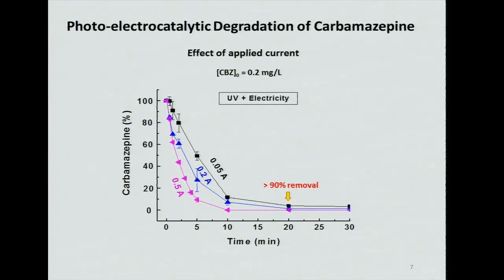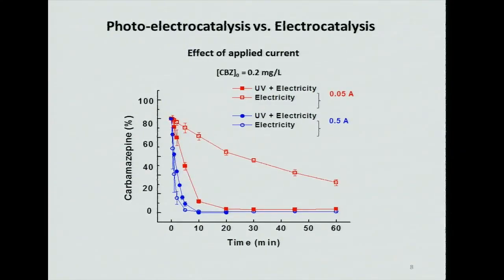Here are the results for degradation of carbamazepine using both UV and electricity. As expected, by increasing the applied current, we obtained higher degradation of carbamazepine. However, for all applied currents, above 90% removal was obtained after about 20 minutes. If we compare the results of the electrocatalysis process with the photoelectrocatalysis process, we find out that at lower currents, the photoelectrocatalysis process works much better for the removal of carbamazepine. But as you can see, at higher currents, both processes worked almost similarly. It indicates that UV energy plays a more important role at lower currents.